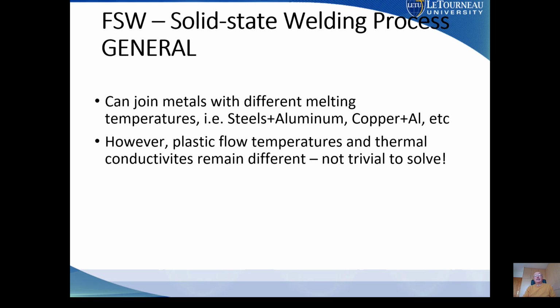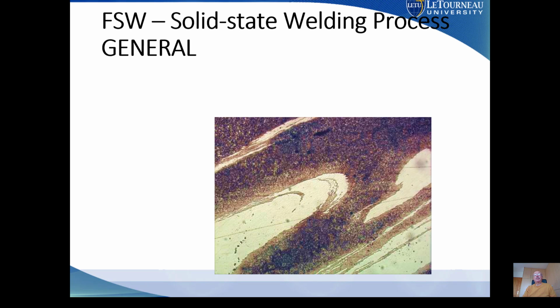So what happens is that it's not a trivial problem to solve, though, the plastic flow of the material. So they don't melt, but they flow at different temperatures. So at the temperature at which aluminum flows, steel doesn't yet, or it just has very high yield strength. So it's not a trivial problem to join two different materials by friction stir welding, although it appears as it is such. And so what happens is that you end up with mixtures, and this is a typical mixture where